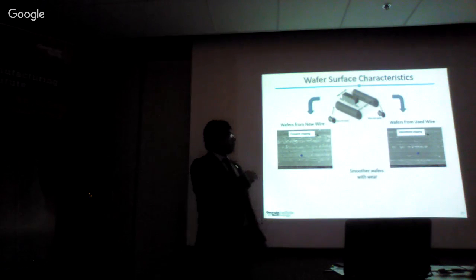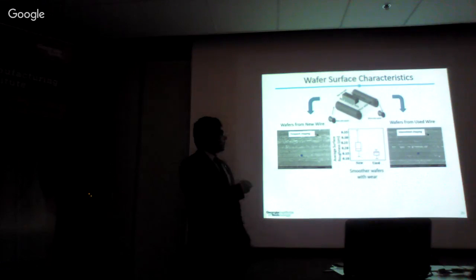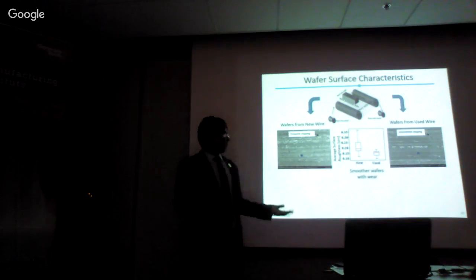When you compare the surface of the wafers cut by the two different wire levels, so we are extracting wafers from the new wire side and wafers from the used wire side, and you just look at the surface morphology by SEM, qualitatively you can see there is a lot more chipping for the wafers cut from the new wire side, whereas the wafers cut from the used wire side show mostly a smooth surface. There are scratch marks and some intermittent chipping. And this was validated by our surface roughness measurement, where we found the wafers cut from the new wire side show a much larger roughness and also a lot of scatter, which means there's a lot more chipping going on. Compared to that, the wafers cut from the used wire side show a smaller roughness and a tighter distribution. So it's much smoother.